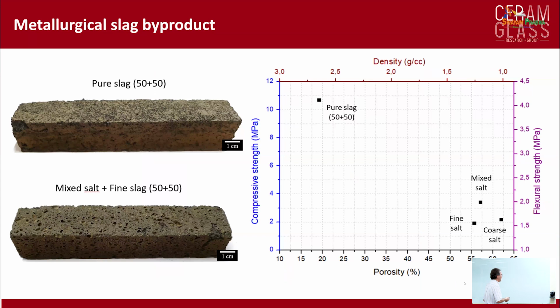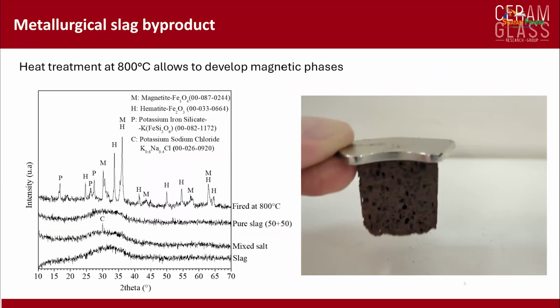You can see the slag and the slag with the salt. And of course, if you increase the porosity, you decrease the strength, so you need to find a balance. One possibly interesting point about this type of geopolymer based on iron silicate is that if you heat treat it to 800 degrees, then you start forming magnetic phases such as magnetite. So you might consider using this material for other applications.